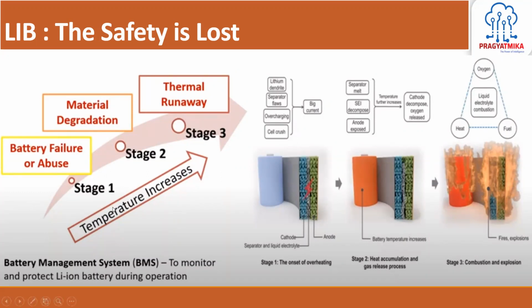In all of this, the temperature starts increasing. It is not a linear increase, it is an exponential increase. Within 5 to 6 minutes, the temperature can go from 40-45 degrees to even 150 or 175 degrees centigrade. Within 11 minutes, everything vanishes off, practically tested. So this is what happens.